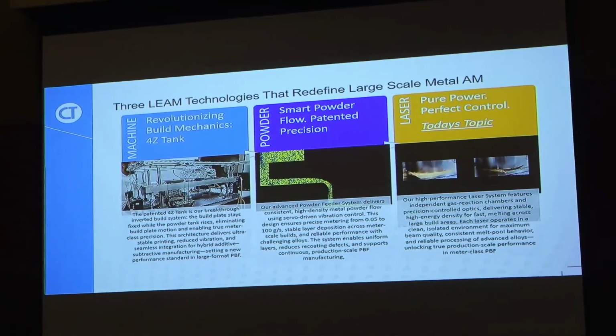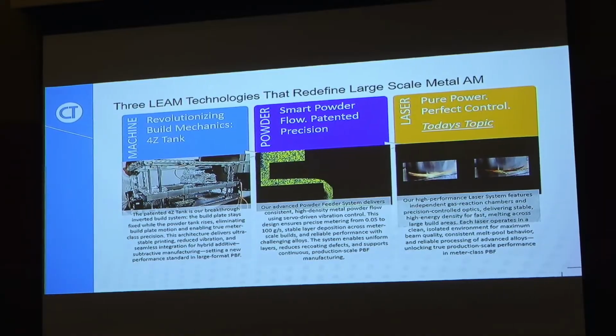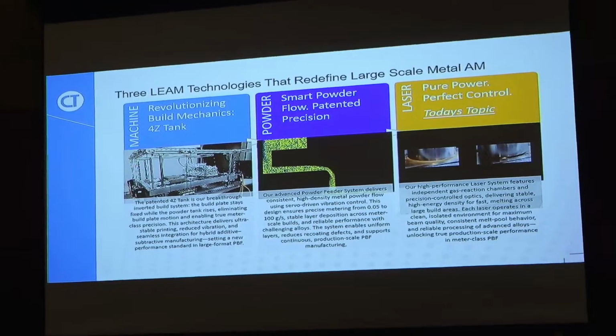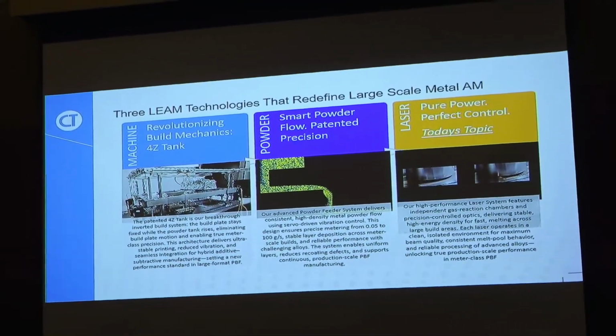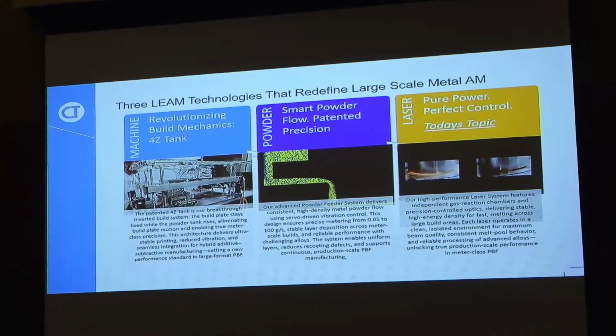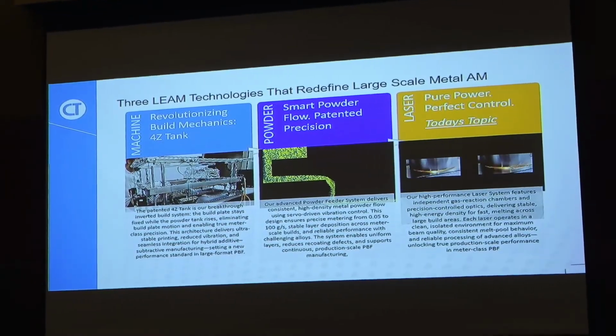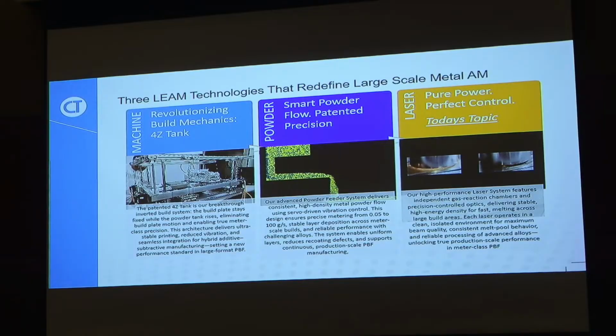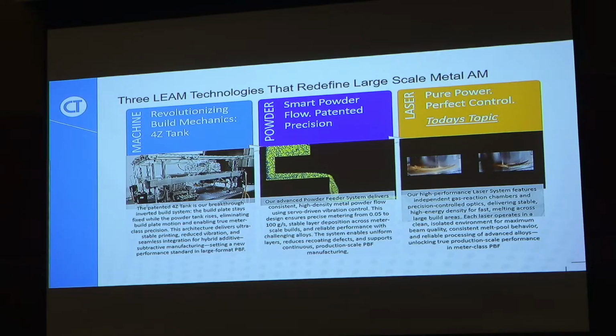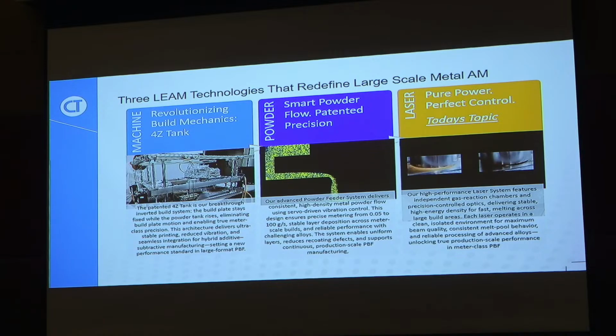approach doing this. On that build plate, we then have what we call smart powder flow. We have a vibration-driven system that is depositing the powder directly over the powder bed. Because if you have a 2 by 2 meter powder bed, you cannot just take a rake and then rake powder over it. So you need really exact dosing in X, Y, and height of your powder layer that you get that actually deposited in the way you want it. It's very, very important that you have a flat and dense layer that you start printing on.